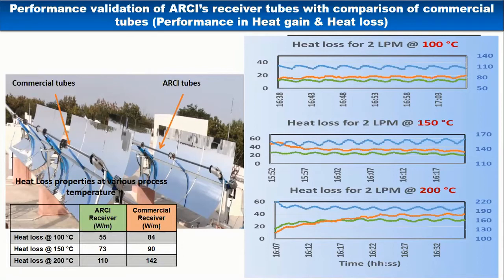Whereas the commercial one is a PVD based receiver tube. After some time, it starts to oxidize. If the metal layer starts to oxidize, the film thickness will go higher. That will kill the radiation and cause high heat loss. In our case, this receiver tube is very stable in open atmospheric condition. That is the advantage of our technology.